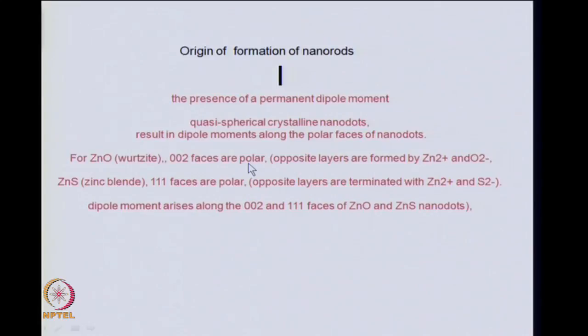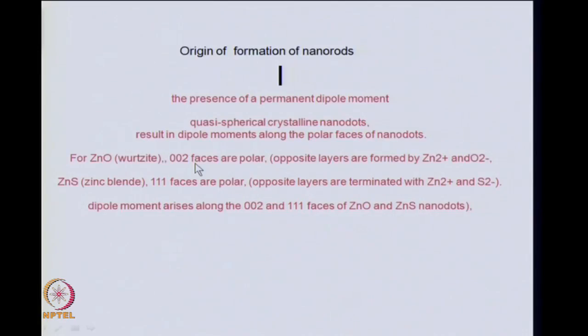are polar faces, that means they have some polarity, and two opposing 002 faces have zinc 2 plus ions on one surface and oxide 2 minus ions on the other surface. So one surface of the 002 is positive and the opposite 002 face is negative. Now, the next zinc 2 plus ion will come closer to the 002 face which is negative, that is, which is having oxide ion terminating on the surface. And this way, the process is continued by oriented attachment led by this permanent dipole moment, which is present in these polar systems.